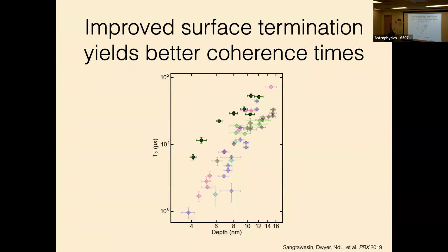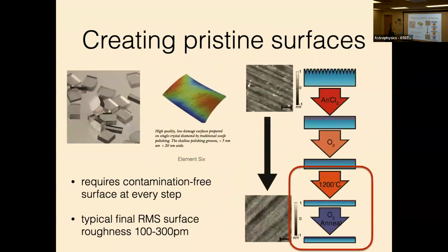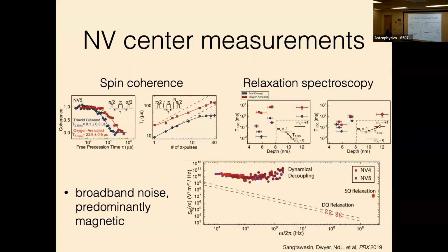So now if you don't want to know anything else, you can fall asleep for the next 5 minutes because this is sort of the takeaway message. But what we can do to try to understand what the source of noise is, is zoom in on these final two surfaces before and after this last oxygen annealing step. And we can look at comparisons of individual NV centers before and after this step.